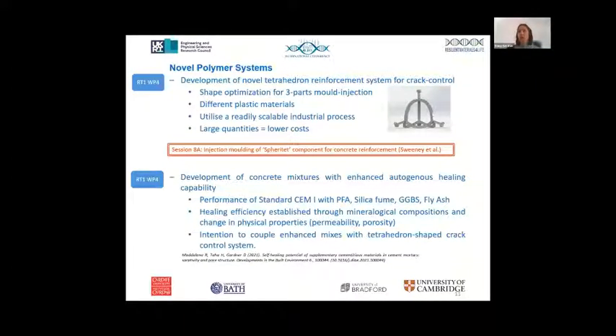And together with these crack closure techniques, we need to have a mix which is really efficient in autogenic healing, a huge autogenic healing potential. So we're looking at our standard mixes with our common cement replacement materials, that will allow us to have autogenic healing perhaps at different ages, to perhaps maximize it at early age, or to have sufficient in reserve for later scale damage when we need that healing action.